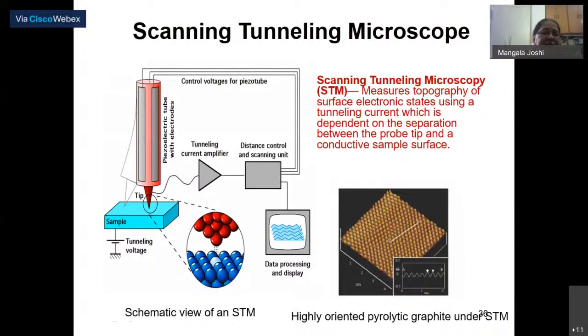If you look at scanning tunneling microscopy, here I am showing you the picture. On the left hand side, you can see there is a sample, the blue one. Then there is a probe, and the probe has a tip, that red tip, which is almost coming in contact with the sample. The probe has certain kinds of atoms and the sample has certain kinds of atoms: the sample has blue atoms and the tip has red atoms. When the probe is brought near to the sample, the interactions between atoms of the tip and atoms of the sample are recorded. It also controls the topography of the sample, and that small tunneling current which is generated is picked up, amplified and then recorded.